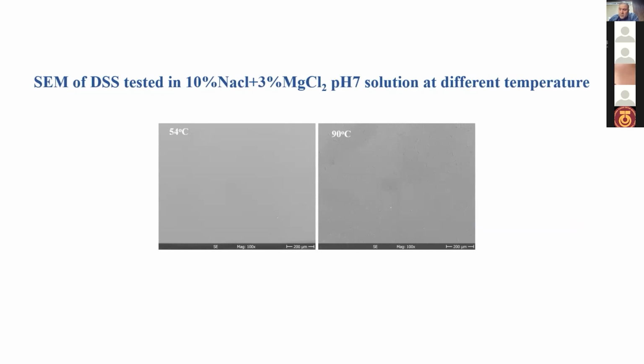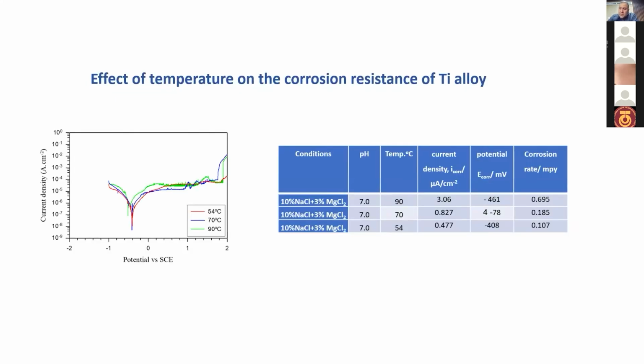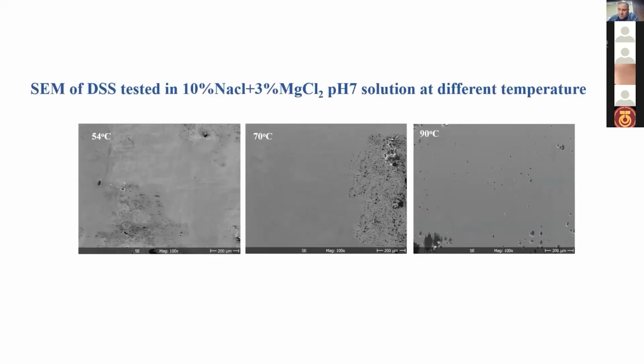So we can explain these results. The results deduced from the electrochemical experiments and the metallographic observation confirm that temperature plays a crucial role in influencing the corrosion resistance. The high corrosion rate of duplex stainless steel may be related to the high dissolution and instability of the oxide film at 90 degrees centigrade, and this is in good agreement with previous studies.